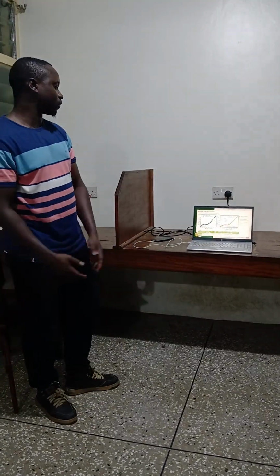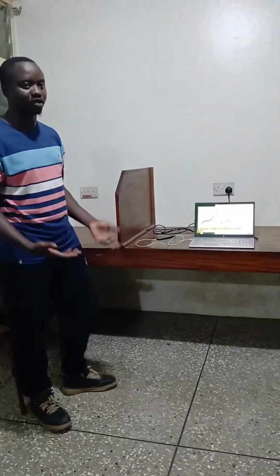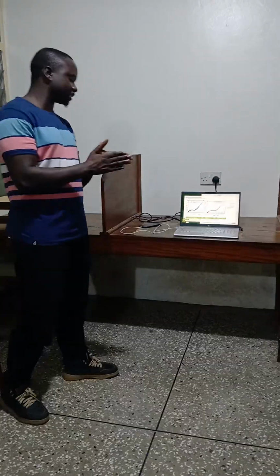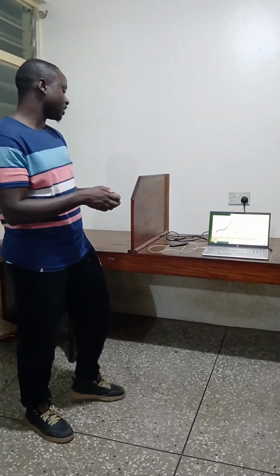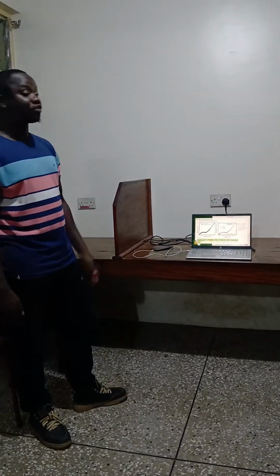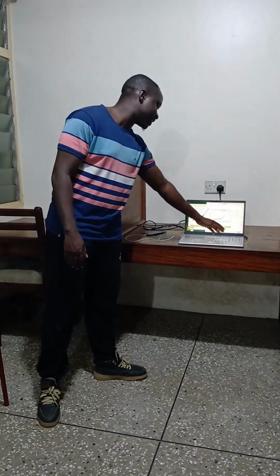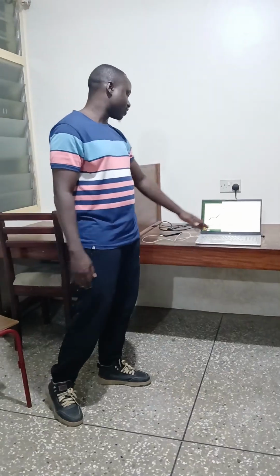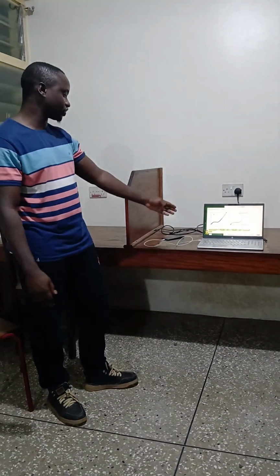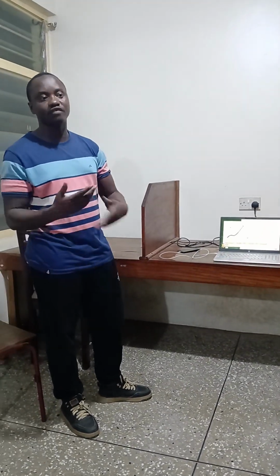For the EIS analysis, we conducted an EIS analysis and we also did an equivalent circuit model to be able to determine the behavior of the material. As you can see, the Rs is very low. There is a limited amount of solution resistance there, but the charge transfer resistance is around 27. For the diffusion resistance, because the material is completely diffused and limited, it is almost 0.0888. That tells us that our material is very good and it has limited amounts of resistance. The CPE that you see here is because of the porosity of the material. So that tells us that the material is also very porous.